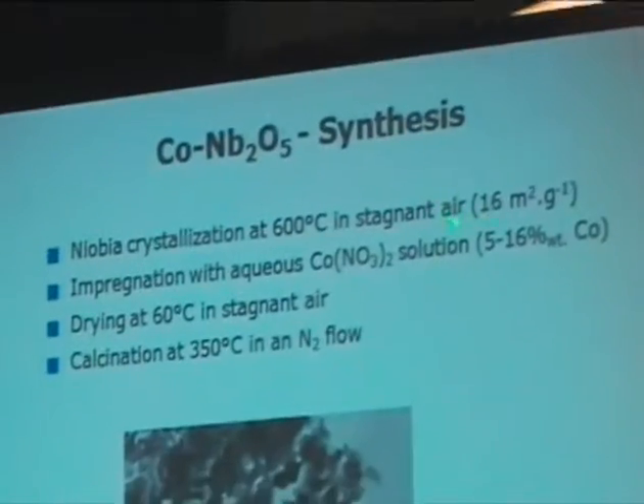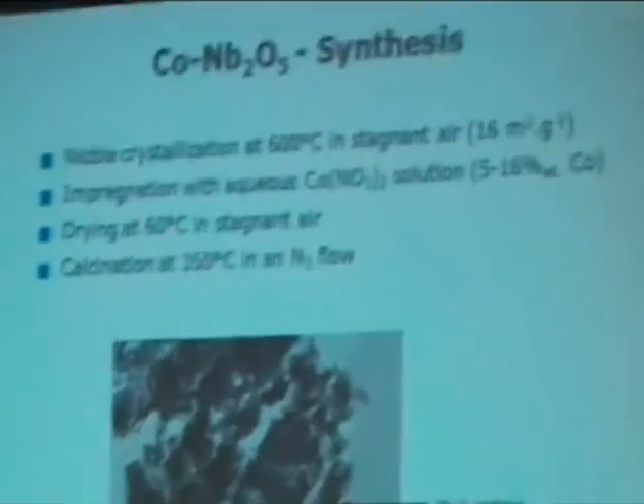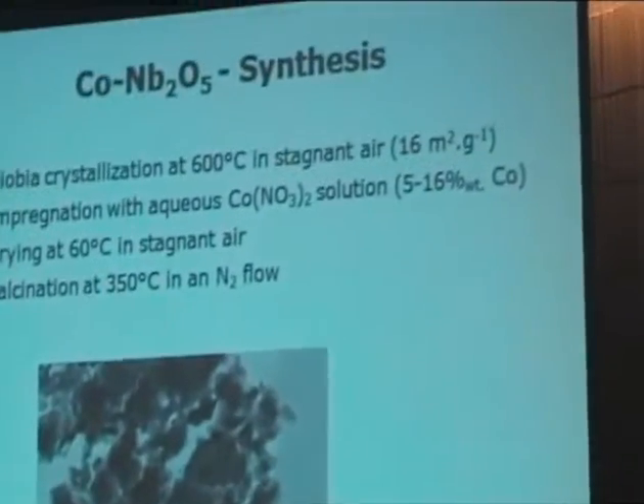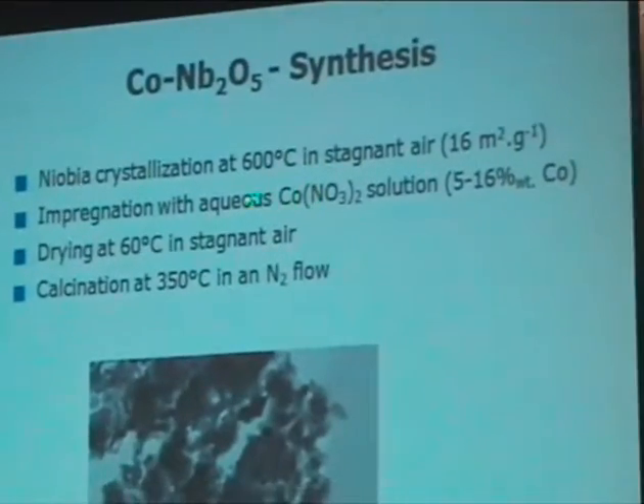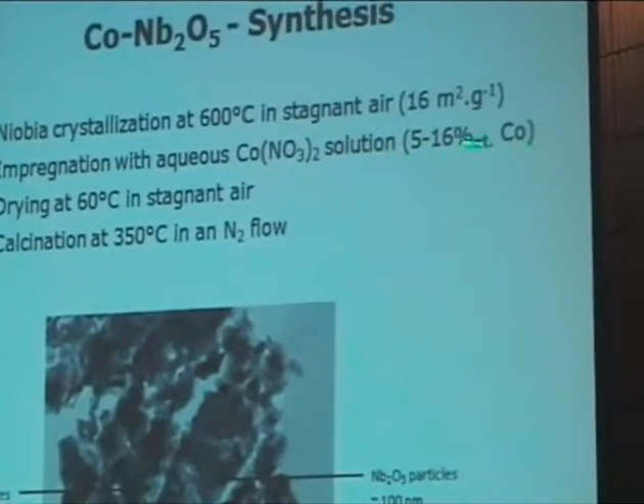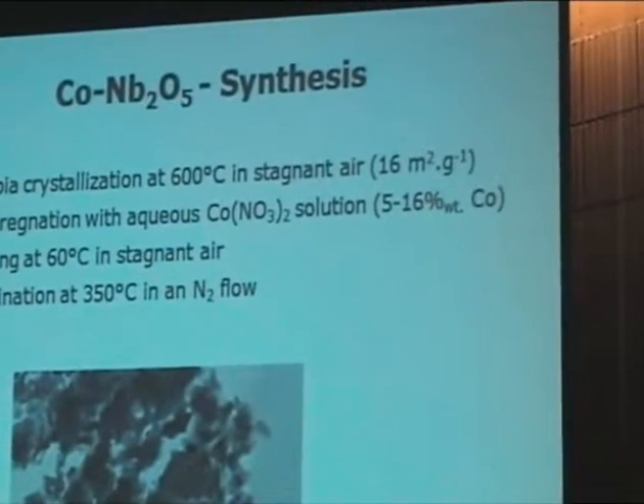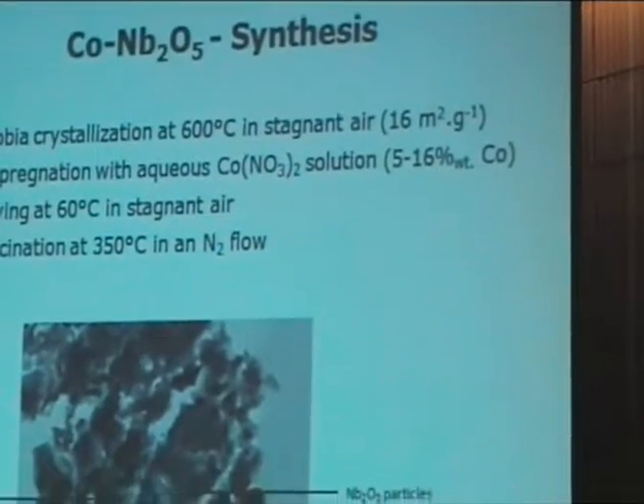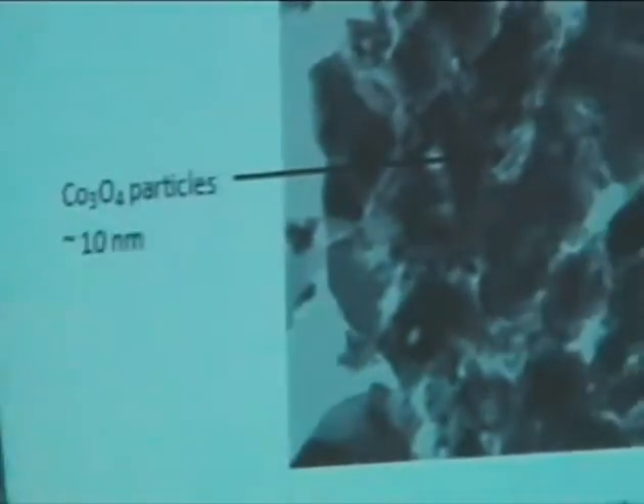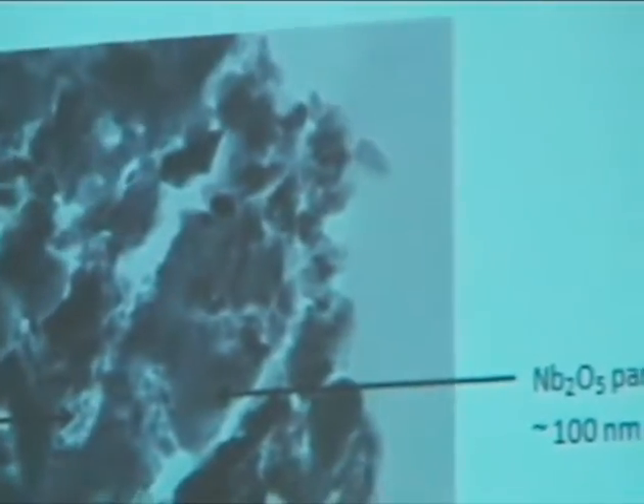elevated temperatures, which implies you have a low surface area support, which seems a poor proposition for an FT catalyst, and usually you require high metal loadings. And of course you can achieve high metal loading by multiple impregnations, but still the dispersion of the cobalt will go down. To illustrate that problem, if you have 11 weight percent of cobalt, these are the niobium particles, quite large, something like 100 nanometers in size, and here are clustered cobalt particles that Stu Soled once called graveyards for catalysis. So that's not a very good proposition.